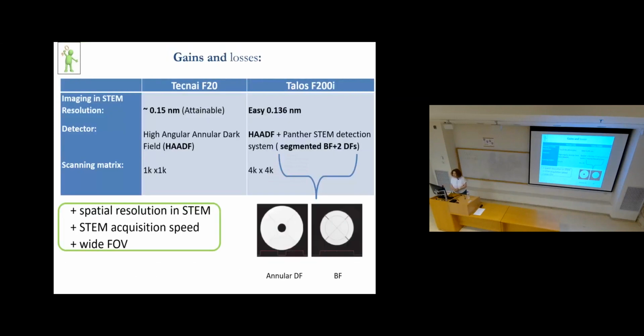Okay, so now we are coming to the scanning transmission electron microscopy. So in the past, when we acquired F20, it was fully blown dream configuration with everything that was available at that time on the market for high resolution and analytical TEM. Okay, so at that time, what was available was only one STEM detector, high annular dark field STEM. So our TEM had only one STEM detector, limited by the information, we will talk about that later, and the matrix was 1K by 1K, and the resolution in STEM mode was attainable. So in the specs, it was written attainable 1.5 angstrom.